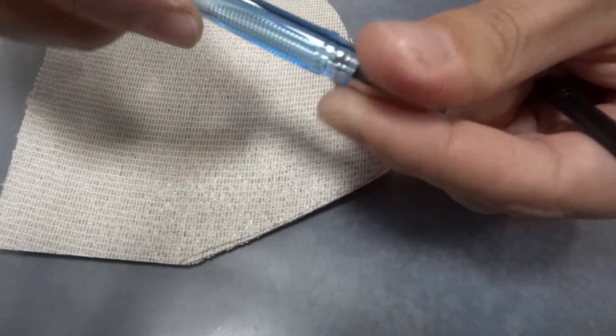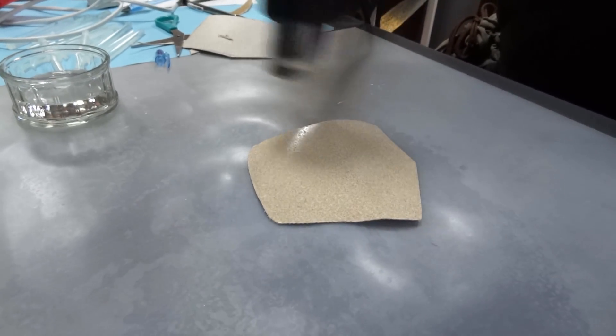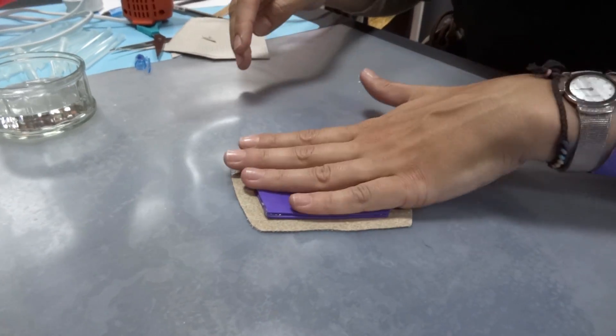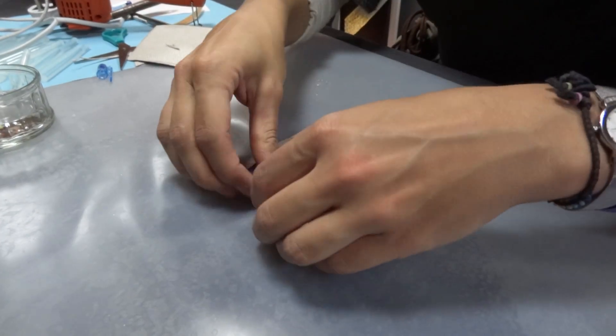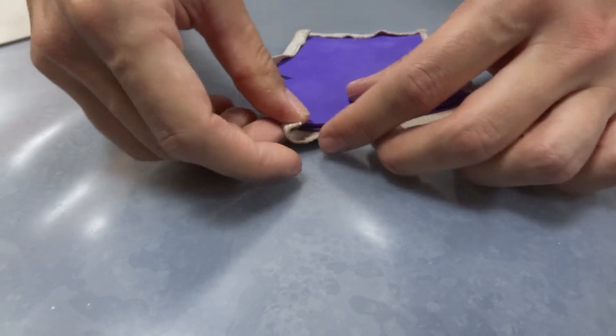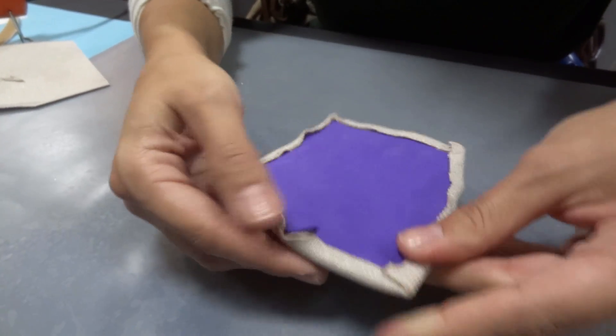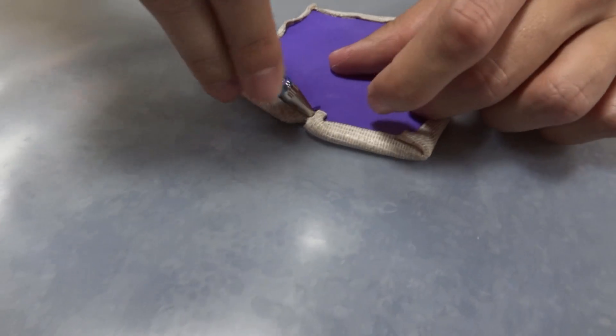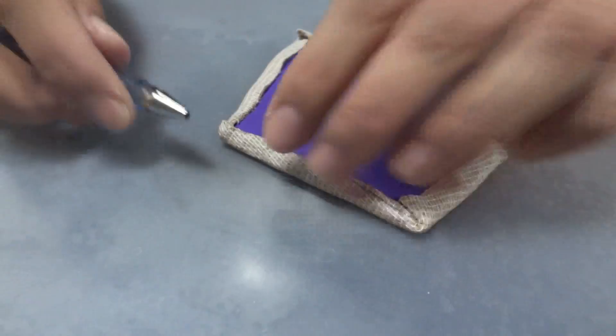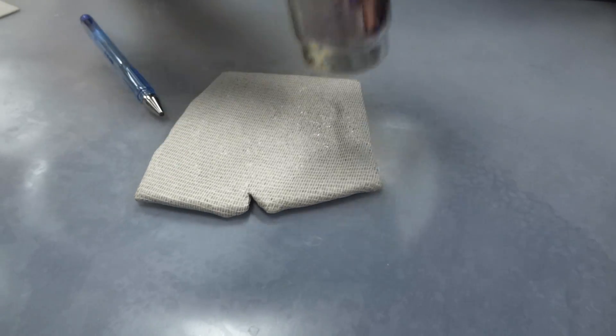It's got its own glue built into it, which is like glue gun glue — it's heat activated. So the whole thing is basically glue, and it sticks to foam really well. If it's not sticking it's usually because it's got cold. I just get a pen, roll it, and you get a really neat finish. That's the trick with Worbla — you just need to keep working it. If it's looking lumpy, just keep working it. I've not used this kind of fabric-backed Worbla before, but we'll see. I'm dipping my finger in water so I don't burn myself. You can start to see it's really picking out the detail now.